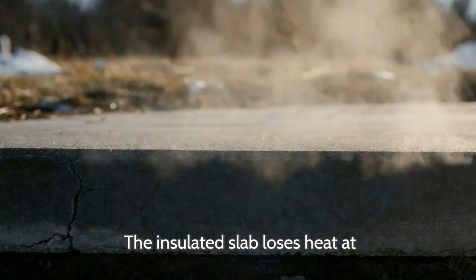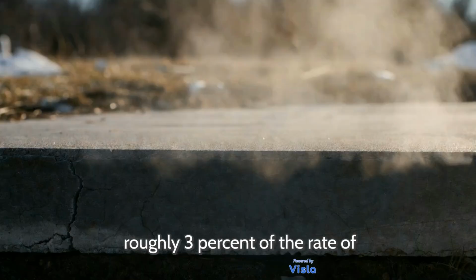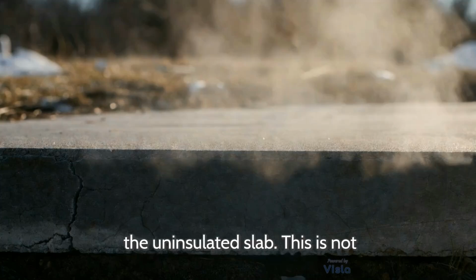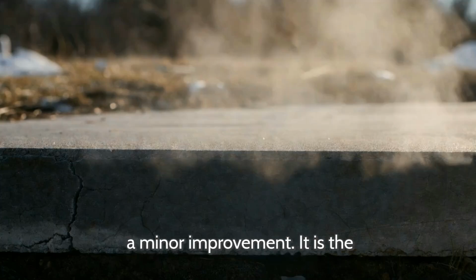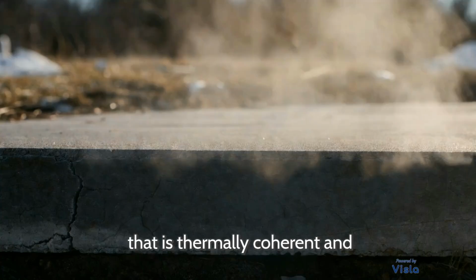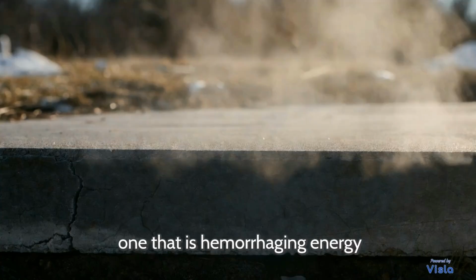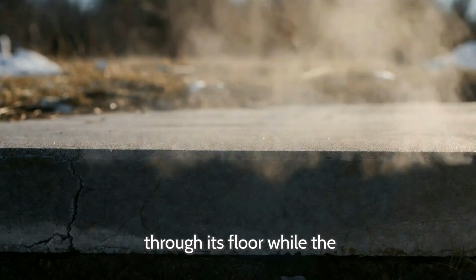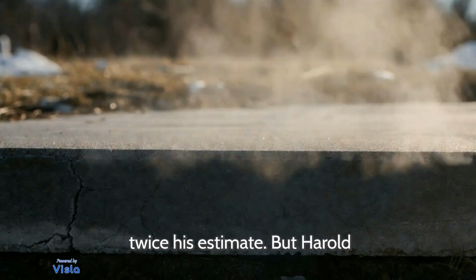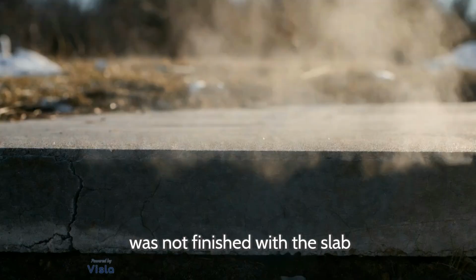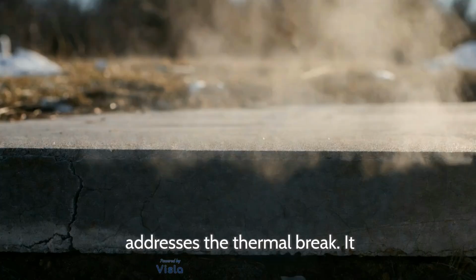The insulated slab loses heat at roughly 3% of the rate of the uninsulated slab. This is not a minor improvement. It is the difference between a structure that is thermally coherent and one that is hemorrhaging energy through its floor, while the builder stands at it puzzling over why his consumption is twice his estimate. But Harold was not finished with the slab system. The XPS board alone addresses the thermal break.